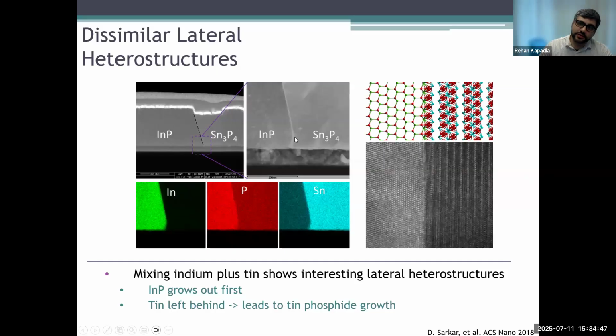And so this was really interesting to us because what it told us is that the way this works is that when we take a template, we put indium in there, we put tin in there, we expose it to phosphorus, what ends up happening is that because of the thermodynamics of indium phosphide precipitating versus the thermodynamics of tin phosphide precipitating, indium phosphide precipitates out first. And so what ends up happening is you just grow half of your template into an indium phosphide crystal, and then you're just left with a bunch of tin. Then the phosphorus keeps coming in, and then you grow tin phosphide.